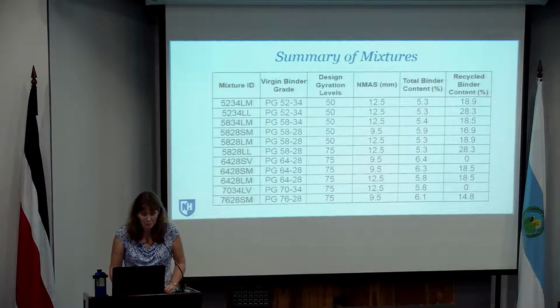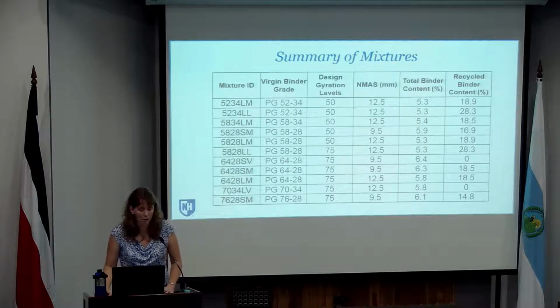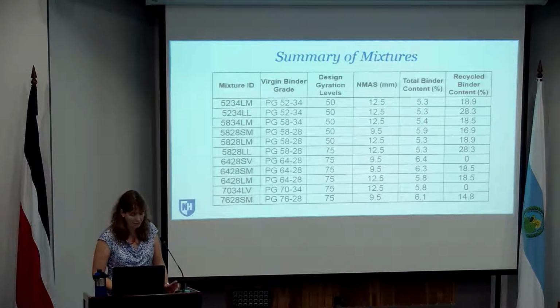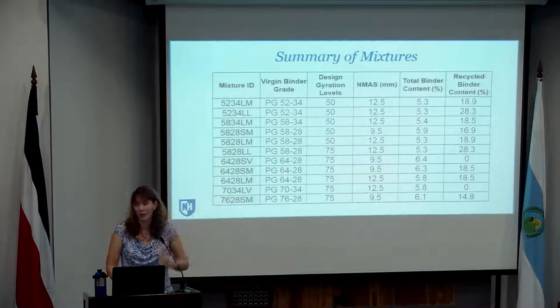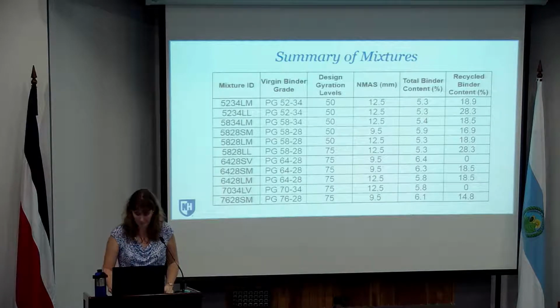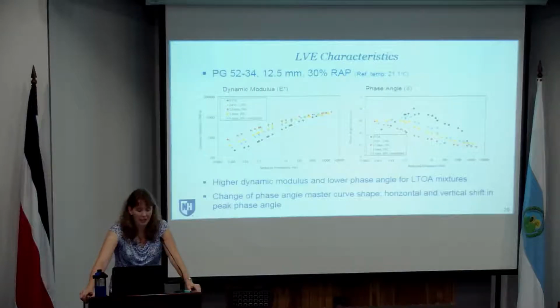So you can see we've got, again, a range of asphalt binders. In this project, we added different design gyration levels, so different types of mixtures for different tiers of roadways, more of the 12.5 and 9.5 millimeter mixtures, and then a range of recycled binder contents. We also included a couple virgin mixtures and a couple of the specialty mixtures that New Hampshire DOT is using a lot more for some of the specific applications. So we've got a 70-34 and also a 76-28, and these are polymer modified materials. So just a couple of examples.